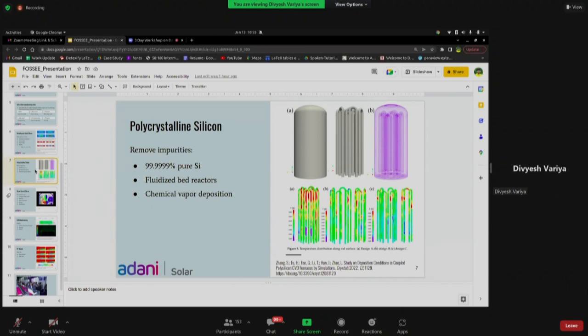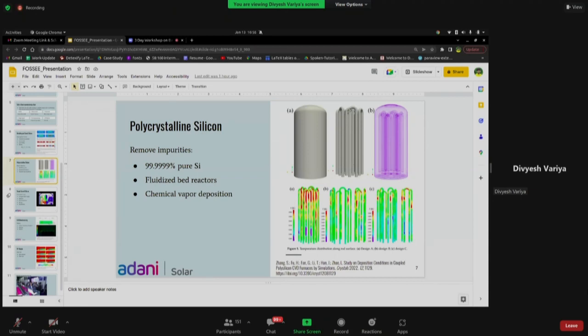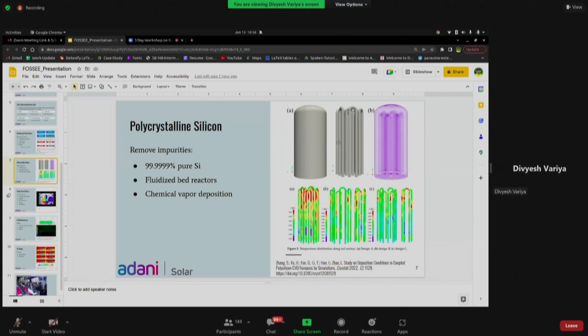After metallurgical grade silicon, we purify it so that the impurity is 0.0001% in the silicon. There are a lot of chemical processes — it's like a huge chemical plant with fluidized reactors, columns, and many things. At the end, the special equipment is called the Siemens reactor, where chemical vapor deposition (CVD) happens. Metallurgical silicon is passed through the bottom of the reactor, reacts with gases, and pure silicon starts depositing on the surface of seed crystals while impurities react with gases and come out of the reactor.